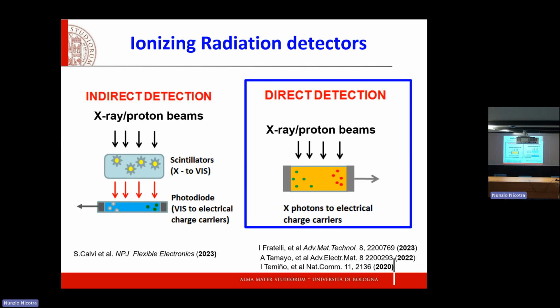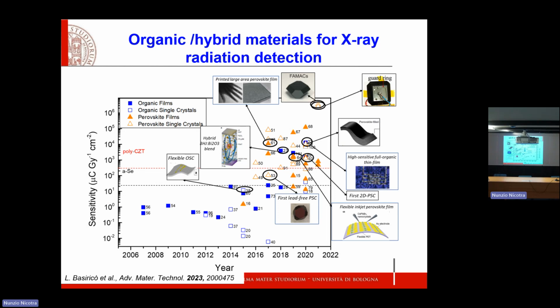The other approach, indirect detection, is a two-step process that uses the incoming radiation hitting onto a scintillator. So the X-ray or the proton beams hit the scintillator and produce visible photons. The energy is downgraded to visible photons, and these visible photons are sent to a photodiode that then converts visible photons into electron hole pairs. So you need a photodiode or a phototransistor coupled to a scintillator. They both work very efficiently. There are examples in the literature with inorganic materials. And today I will show you what we do with organic and perovskite materials in this respect.